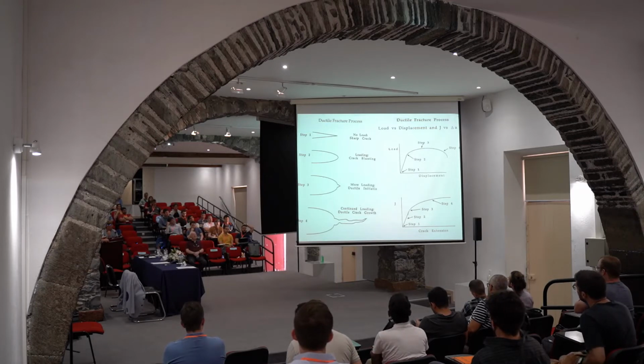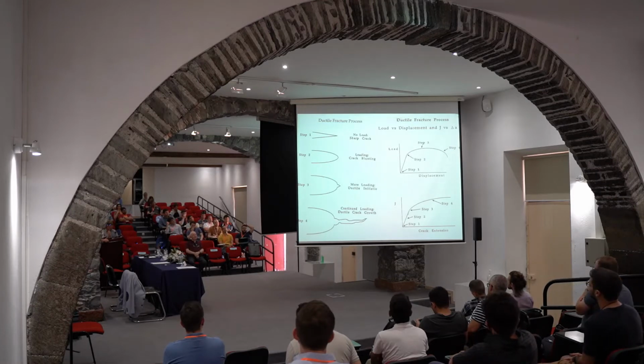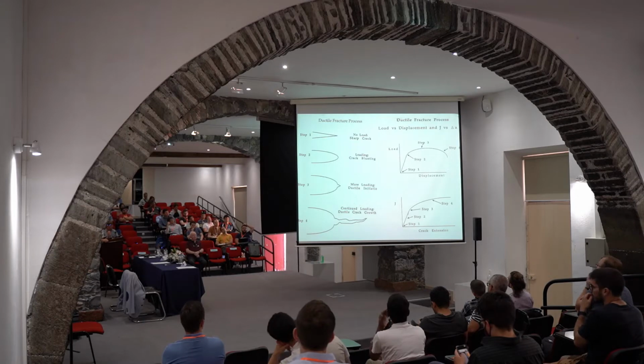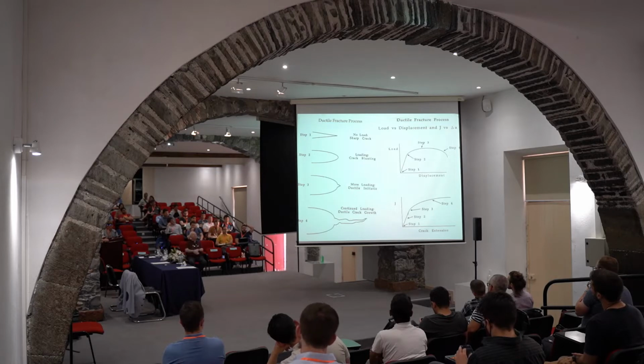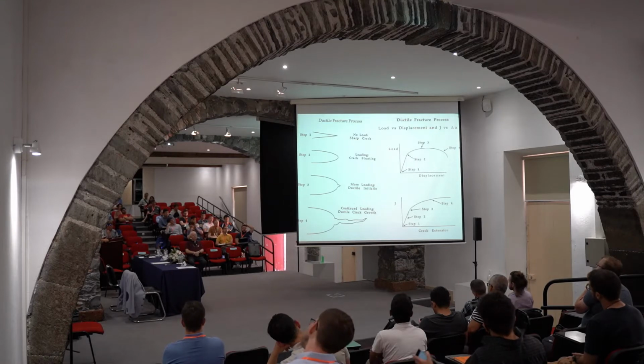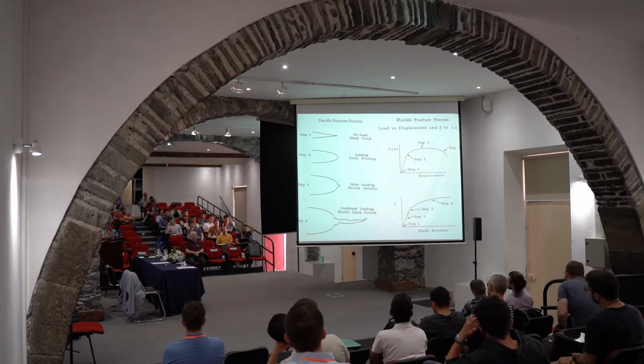So, what I just described is the ductile fracture process. You can see here 4 steps. Without the load, there is just a sharp crack, then the crack blunts, and then initiation of crack growth is step 3, and its further growth, ductile crack growth, is step 4. These steps are also marked here on the load displacement curve, and finally this right bottom curve is the JR curve. This is J versus crack extension, and you can see the steps marked there.